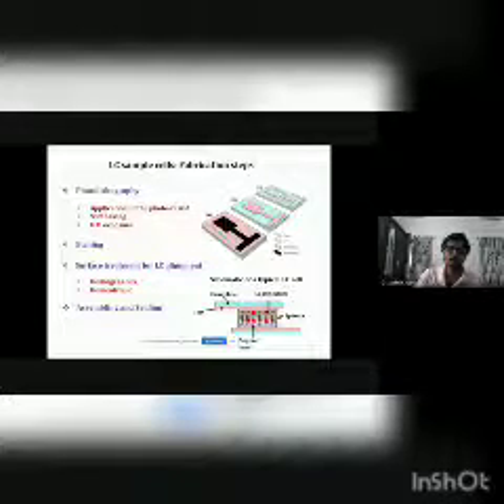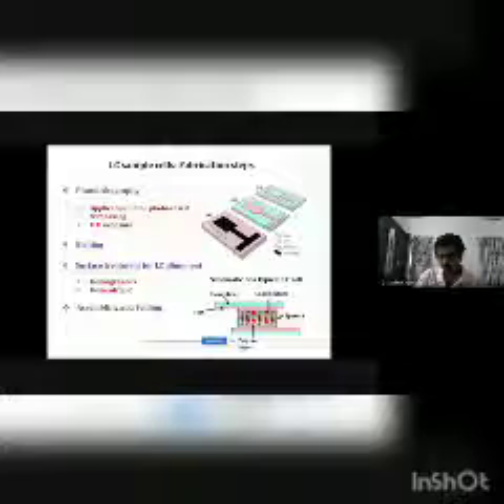And you will have a polymer layer here for giving this homogeneous alignment to these molecules. And if you need a homeotropic alignment, you have to use a silane type of surface treatment, which will have perpendicular molecular orientations. So normally we prefer homogeneous alignment in these molecules. Again, you can make a contact on this ITO by using indium ingots. So typically, after assembling and sealing, the molecules are properly aligned and the whole device will look like this.